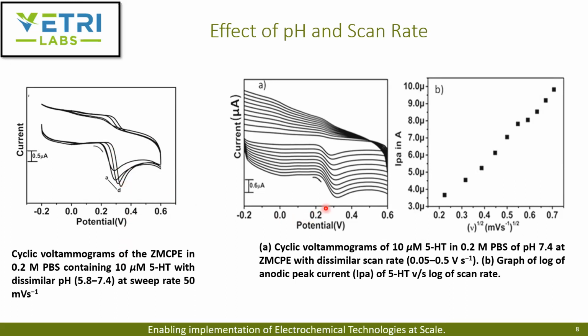To identify if the reaction is indeed diffusion controlled or not, they used CV on 10 micromolar serotonin in a 0.2 molar buffer solution at 7.4 pH, and they changed the scan rate from 0.05 volts per second to 0.5 volt per second. They recorded the anodic peak current, extracted it and plotted it versus the square root of the scan rate, and they found it to be linear with a correlation coefficient of about 0.994. This confirms that the electron transfer process is diffusion controlled.